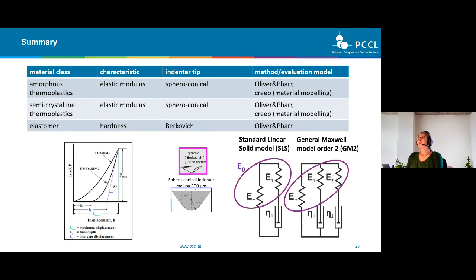Now I would like to give you a short summary. We have seen if we want to indent an amorphous thermoplastic and get the elastic modulus, we should use a spheroconical indenter tip with a large radius. For evaluation, we can use the simple Oliver and Pharr method, but we could also use the creep in combination with material modeling.